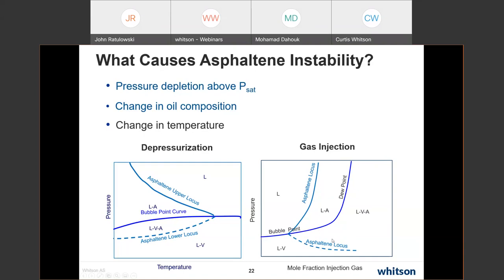So that is one thing you have to be concerned about with gas injection processes for asphaltic oils: change in temperature. You look at this asphaltene locus, and it is a function of temperature, as it must be. However, when we look at our production path, usually we're coming down from high pressure into lower temperatures and lower pressure. So by the time we get to these really low temperatures, we're already down below the bubble point. So it's really the compositional changes that are dominating, not so much the temperature.